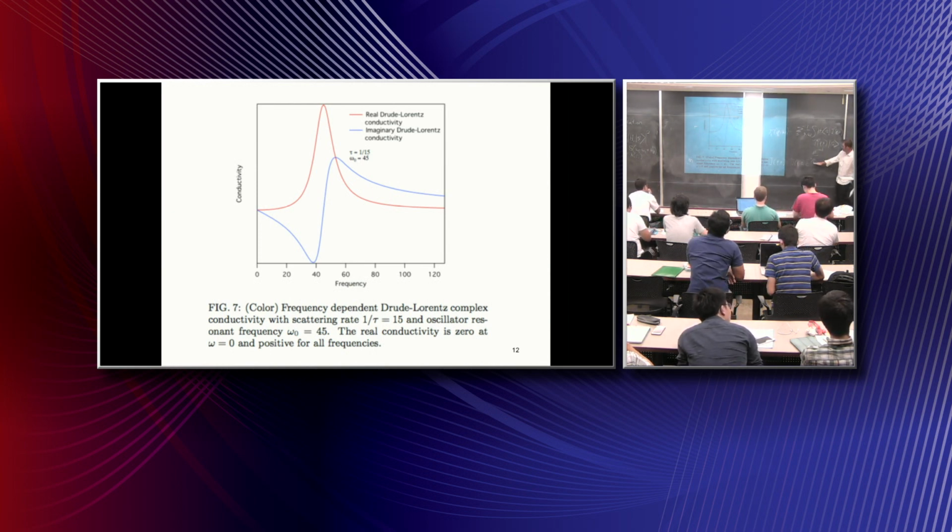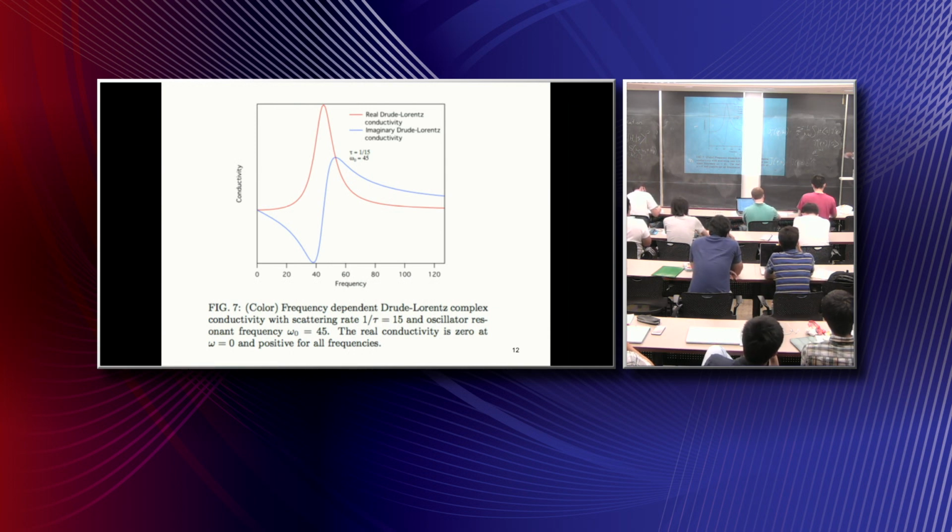Okay, so if I substitute this expression in and continue the calculation, what comes out of this purely quantum mechanical calculation is exactly the Drude model expression. This is why, even though we're dealing with very quantum mechanical particles, the Drude model, this classical model, is still a good starting point, because the first term in the quantum mechanical calculation is completely reproduced by the semi-classical approximation. In fact, this is why the whole scheme of Boltzmann transport, applied to electrons moving in solids, works at all. There's a huge field of people trying to calculate the next terms in this, referred to generically as quantum corrections.